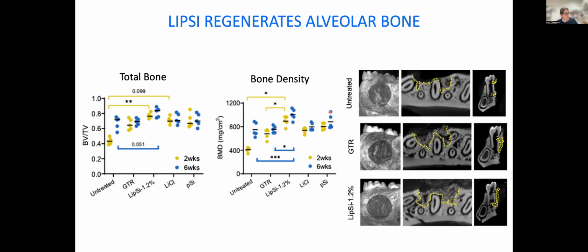And in the end, if we take a mouse model where we generate a defect both in the bone and in the ligament and in the tooth, we see that with our lithiated porous silicon, we get a much better regeneration, both in terms of the total amount of bone and the density of bone, than with either introducing porous silicon or introducing lithium chloride, or using what is the gold standard in terms of periodontal regeneration, which is a guided tissue regeneration membrane. And obviously this improves against the non-treated control.